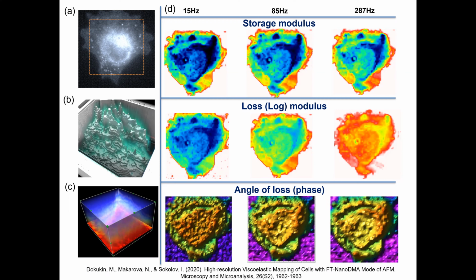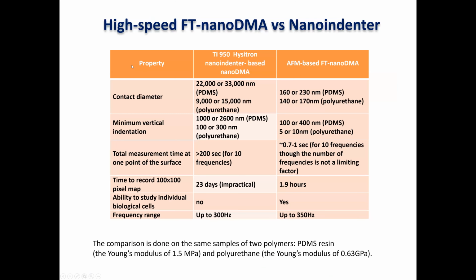And the loss modulus is changing dramatically, and in particular, this is a log scale. You also see some kind of bumps and some protrusions which are not seen in the optical image. So when you have 25 maps, it's always a question how you present it. You can use multiple presentations: this is an equipotential surface, or this is a 3D semi-transparent cube, and so on. This is, by the way, the loss angle, phase. And you can also clearly see the nucleus here. And again, multiple things which are definitely not seen in the optical image. So this is just to give you some flavor.